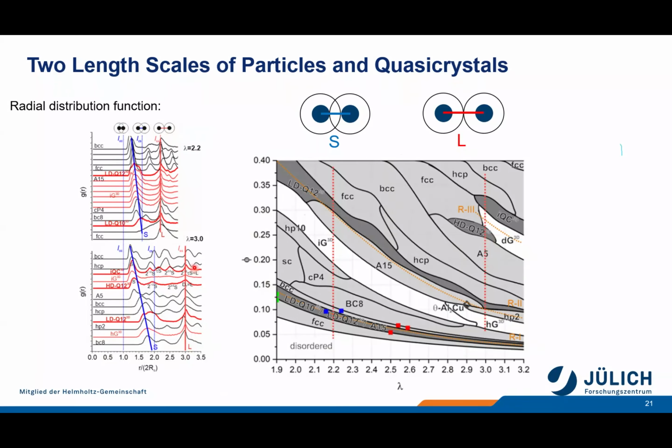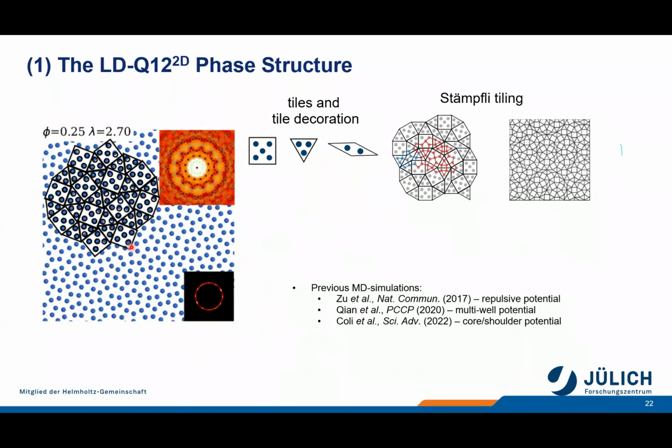So if we increase the volume fraction, we have the length scale of the edge-edge contact of the outer shell, but we also see how we squeeze together the shell such that at the end, we nearly have a core-core contact as the second short length scale. So this two length scale thing is really important, and it's a typical feature of quasicrystalline structure, not only in 2D, but also in 3D. And that's a remarkable thing one could learn from such simple core shell particles.